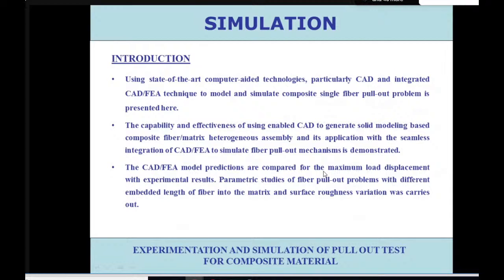Even when we take the theoretical case by the rule of mixture, we say VF, EF, VM, EM: volume fraction of fiber, volume fraction of matrix, and what is the property of fiber, what is the property of matrix. But certain other parameters are also equally important for designing the material, that we have seen by this pull out test, that if the surface area is improved, and that is why now people are using carbon nanotube insertion into the matrix, because at the interface they give tremendous area. 1% of carbon nanotube can increase the percentage of interfacial area to a numerous value. So thereby the property can be improved by incorporating the carbon nanotube.